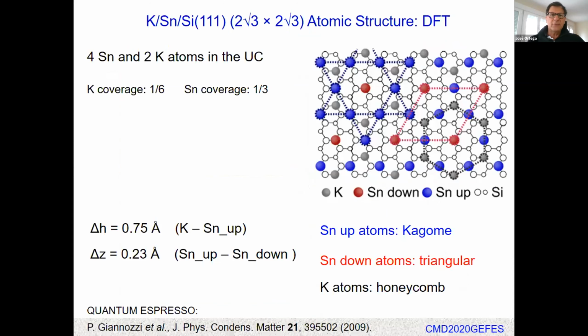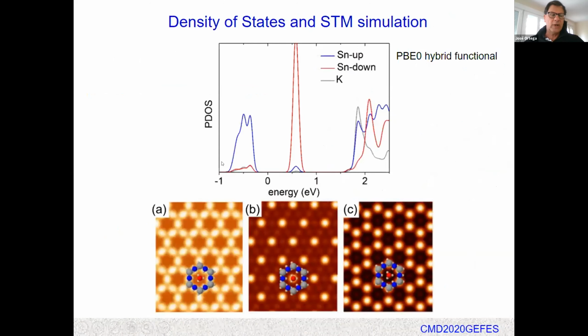So with DFT, we confirm this structure as the lowest energy, most stable one. And we can also obtain some details, for example, the difference between the tin up and tin down heights. The tin up atoms are 0.23 Å higher than the tin down atoms. That's why we call them tin up or tin down. And also the potassium atoms are above the tin up atoms by around 0.75 Å. Also, the calculation of the density of states and the STM simulation confirm the experimental STM images. So this Kagome lattice corresponds to the occupied dangling bonds in the tin up atoms, the triangular lattice corresponds to the empty dangling bonds in the tin down atoms, and the honeycomb lattice corresponds to potassium atoms.